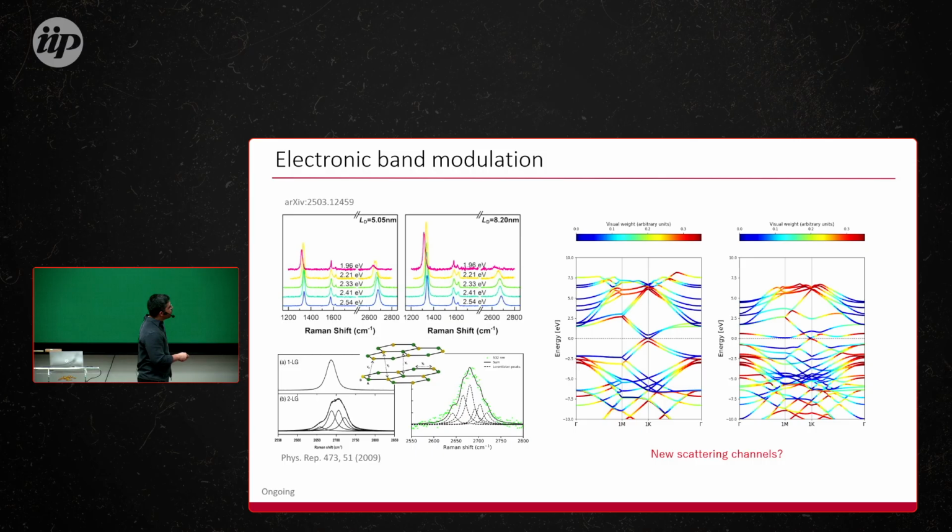And when you have a higher concentration of defects, it becomes something like this. So basically, this top band over here comes quite a little higher. This lower one here in the conduction band starts to split in two. We have one minimum here and another minimum over here. And then those 2 bands over here in the valence band shift, as you can see here.